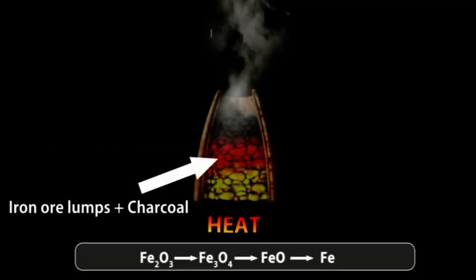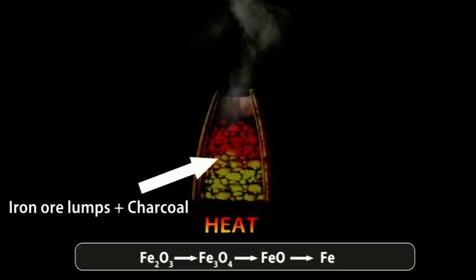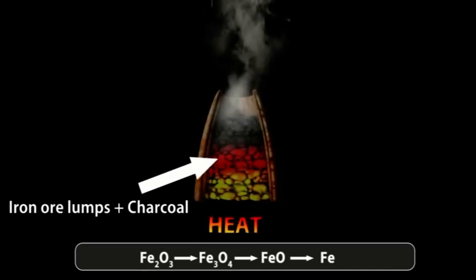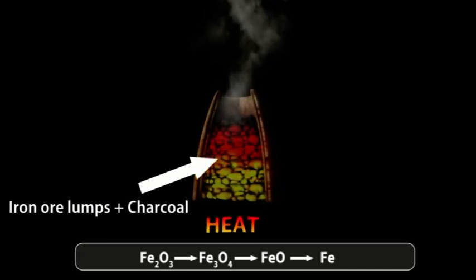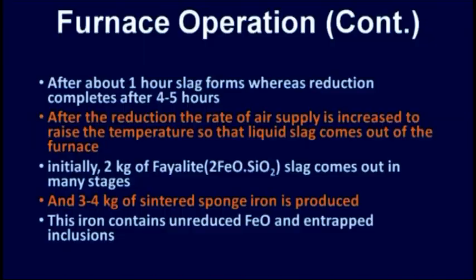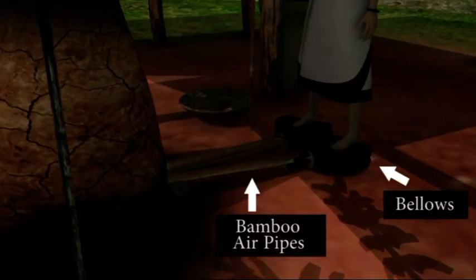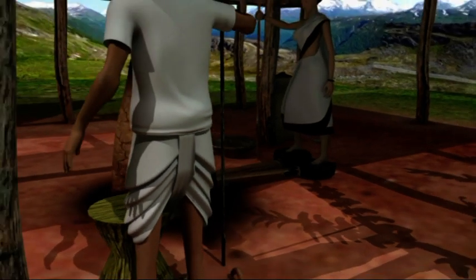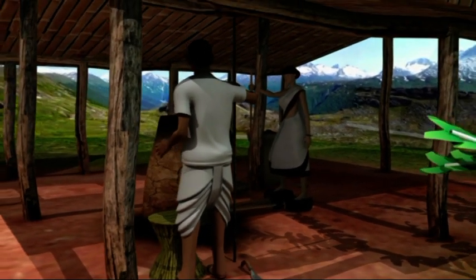After an hour, the temperature reached a level of 1100 to 1200 degrees centigrade. The first slag appears after 1 hour, and the complete reduction takes place after 4-5 hours. After the reduction of iron ore, the air supply is further increased to further increase the temperature, so that the slag will come out in liquid form.